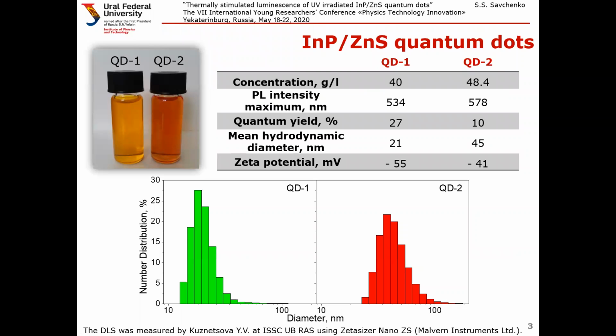Therefore, our work studies photo and thermally stimulated luminescence for two types of the quantum dots, denoted as QD1 and QD2. They have core shell structure coated with modified polyacrylic acid. According to dynamic light scattering, an average diameter and size distribution are smaller for the QD1.